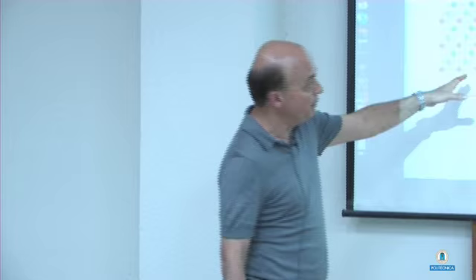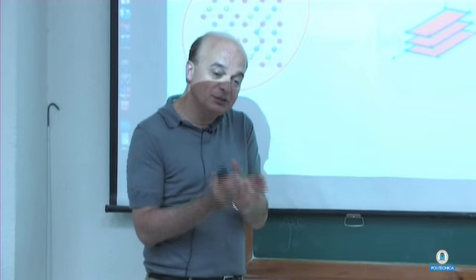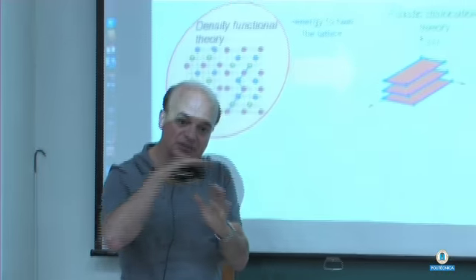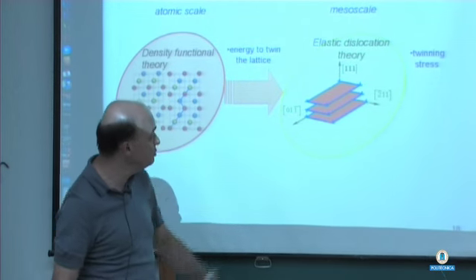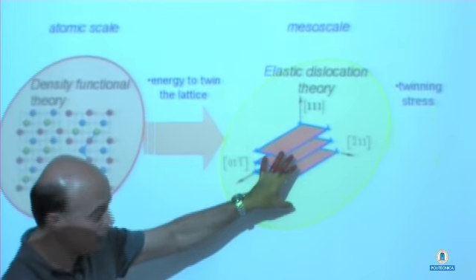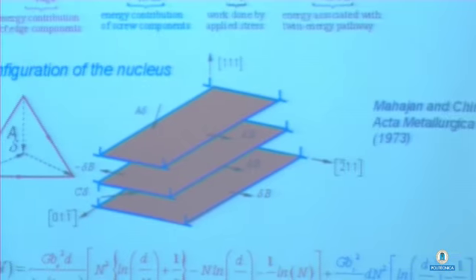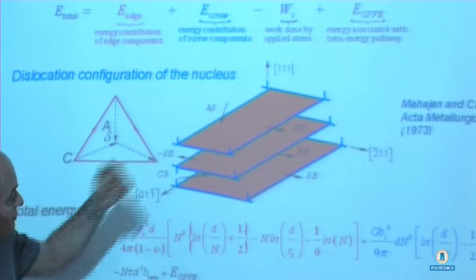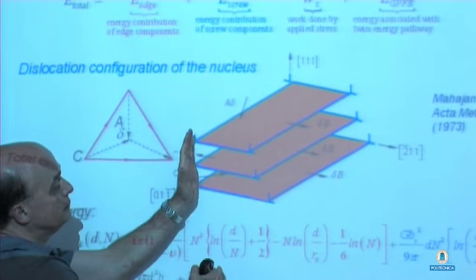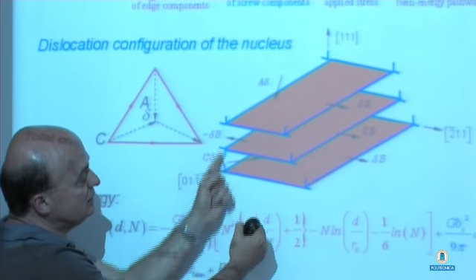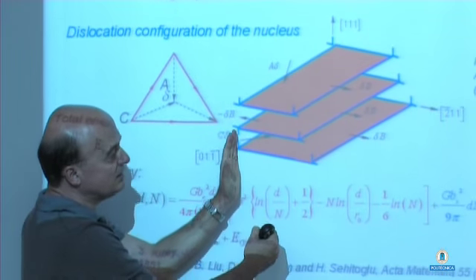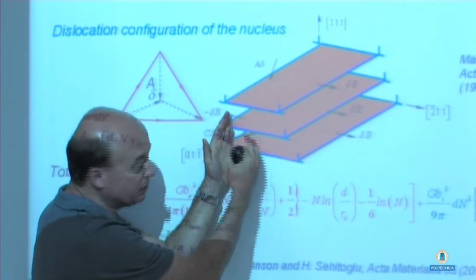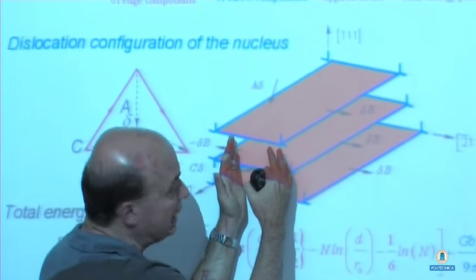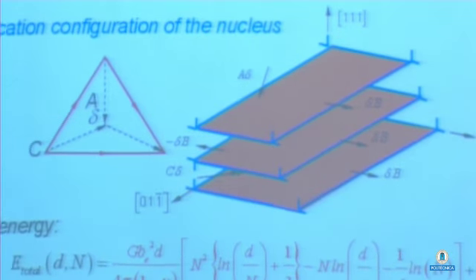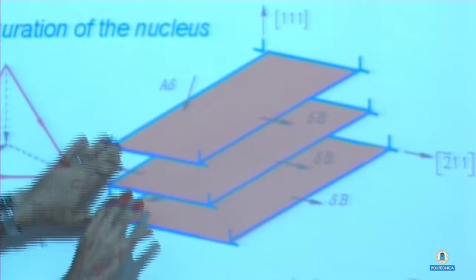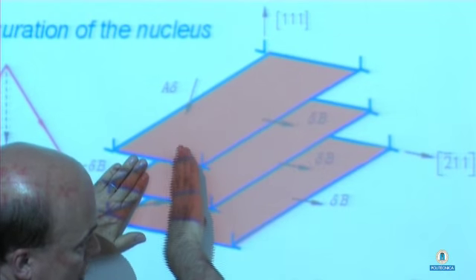So we have density functional theory, and then the twin occurs as a consequence of passage of partial dislocations. So there is a twin nucleus associated with that. And this twin nucleus has dislocations bounding it, and this set of dislocations here are sessile. That means they are stationary. These three here are glissile, they move. So the way the twin will move is that these have both edge and screw components. This set of dislocations move.